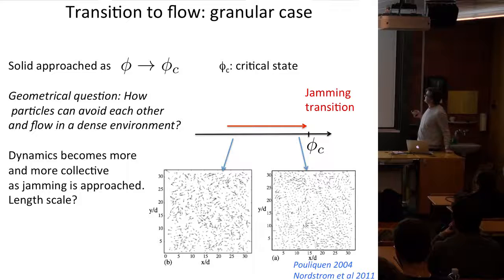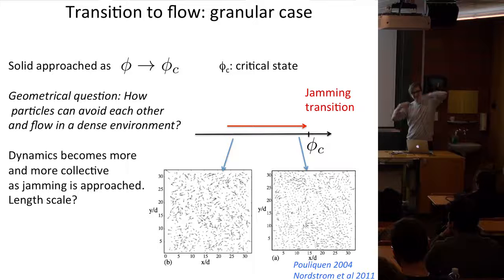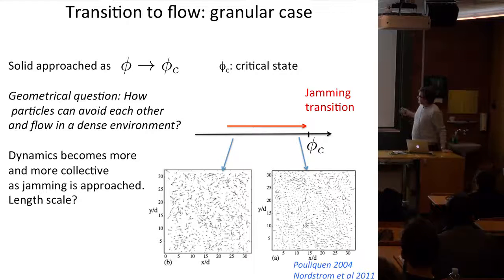So it's essentially the physics of dense granular flows. One way to do it experimentally is you take a layer of sand and you tilt the system. If you tilt it with a large angle, it would flow fast, and the density would be small. But as you lower the angle, the density becomes larger and larger, and at some point, boom, it stops. The packing fraction at which it stops is actually well-defined, and in the field, it's called the critical state. Essentially, that's because you reach a stationary state. If you take a granular material and you shear it quasi-statically for a very long time, the packing fraction may have some transient behavior and you have dilatancy and so on, but eventually it would reach a stationary state. That's called the critical state, and that's a well-defined number.